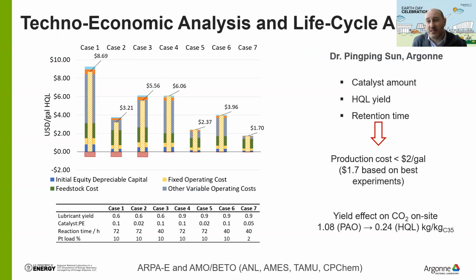Some technoeconomic analysis and life cycle analysis. This is from my colleague, Dr. Pingping Sun, here at Argonne. Very interesting on the LCA. We show, for example, that there is an improvement, or decrease, in GHG from the direct synthesis of polyolefin to making polyolefin using plastic waste. There is roughly 75 to 80% less emission of CO2.